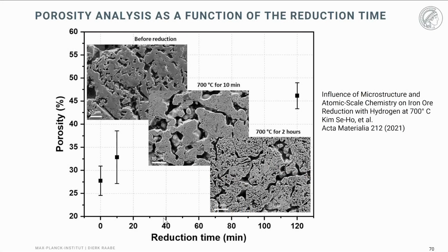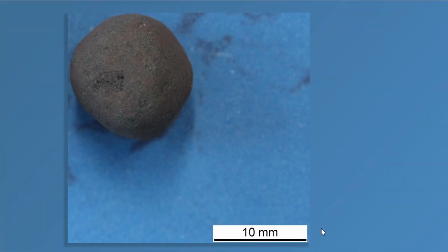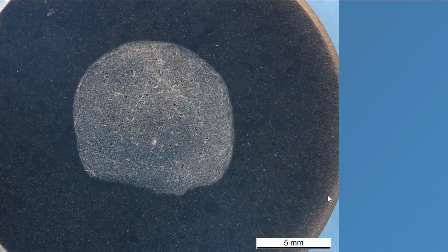This also changes as a function of the reduction time, as you see here in this view graph, with a couple of snapshots at 700 degrees centigrade. After 2 hours, you can see that the material consists of a very, very complicated microstructure with dislocations, grain boundaries, pores, and cracks. Now, if we walk through such a commercial pellet, this little oxide piece that is an agglomerate of fine ores is called a pellet, and it's typically used in direct reduction.